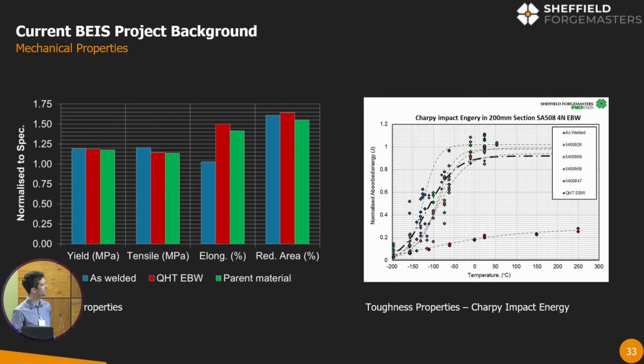And from a toughness perspective, so how much energy can that steel absorb if you hit it with a high speed impact? For pressure vessel applications, you need strength and toughness to resist crack growth. On the right-hand side, that graph is showing the impact behaviour. The low line with the red dots at the bottom, showing low levels of energy absorption over a wide temperature range, is the as-welded condition. But if you heat treat that, there's a thick dotted line throughout all that data, which is the heat-treated material. You can get back up to parent toughnesses, and at lower temperatures, it exceeds the parent material. So really promising for us.